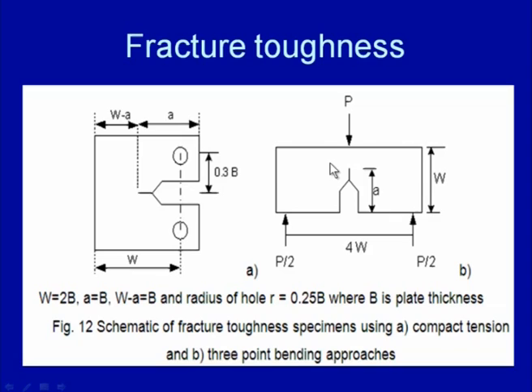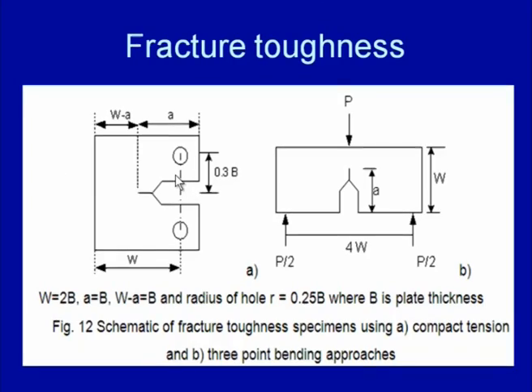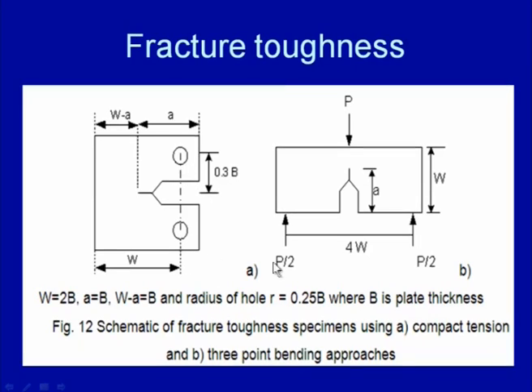Similar dimensions are used here, but in this case the load is applied in a tensile manner for opening of the crack mouth. So, we try to measure under what loading conditions the crack starts to propagate. In case of the 3-point bending specimen, the specimen is simply supported and the bending load is applied from the top like this, and the hole which is made is about 0.25 times the plate thickness.